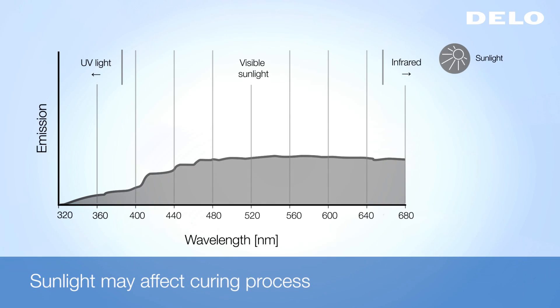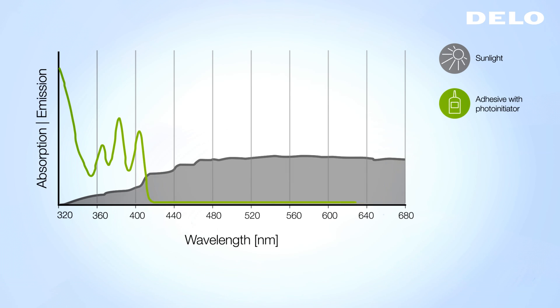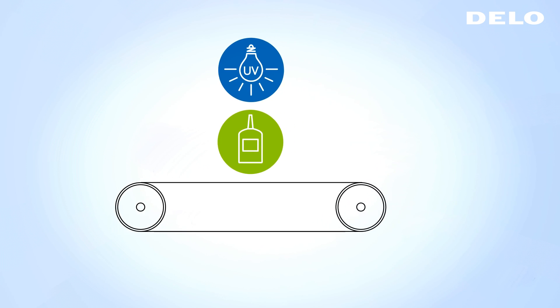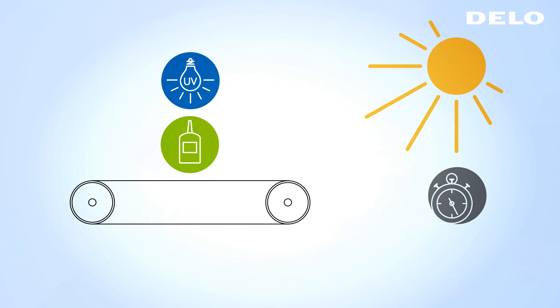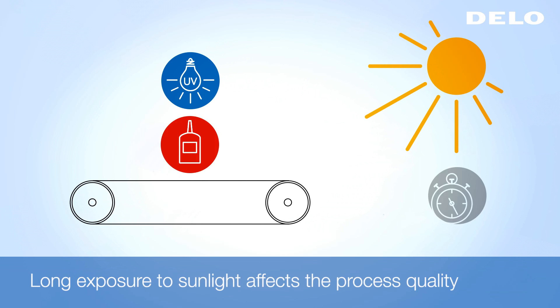For example, sunlight has a broad spectrum also in the relevant area of the photo initiator. While the intensity is too low to fully cure the adhesive, over longer exposure the dispensing nozzle may clog, leading to failure of parts.